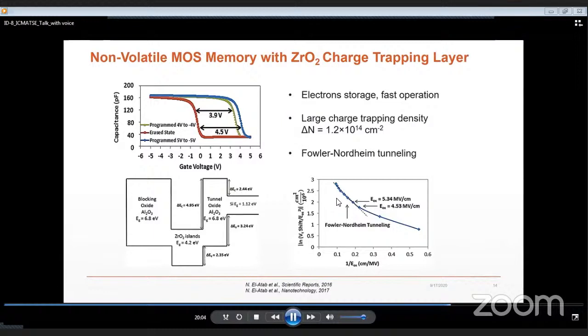And it is shown that the memory devices are being programmed by storing electrons in the zirconia nano islands and erased by removing these electrons from the nano islands, so there was no hole storage. This can be explained using the energy band diagram of the memory. The band diagram shows the formation of a deep quantum well in the nanoislands embedded in the aluminum oxide layers as a result of the conduction band offsets. This deep quantum well enables the storage of the electrons during the programming operation, while there is no quantum well resulting from the valence band offsets, which can prevent the storage of holes and cause their leakage.